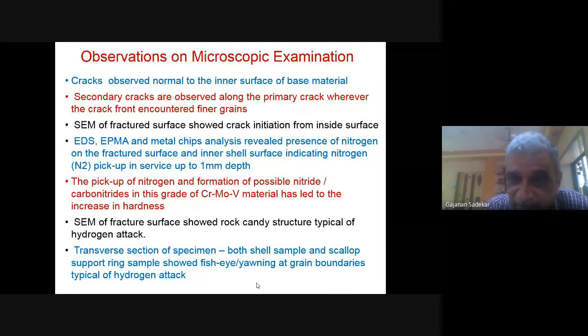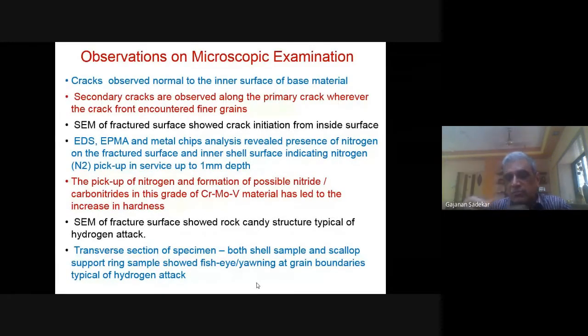the increase in hardness. Why increase in hardness? Because of the grades, the carbonitrides are formed, which will be hardened material. So the hardness has increased. SEM of the fracture surface showed rock candy structure typical of hydrogen attack, and the transverse section of the specimen showed fish-eye yarning of the grain boundaries, typical of hydrogen attack. So that was the conclusion drawn from here.